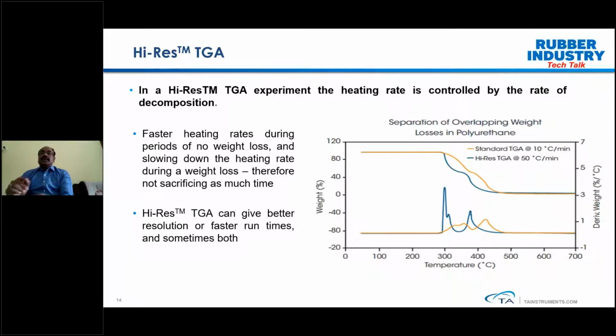Okay, so what we see is a much sharper peak, and you can see the clear shift of your decomposition pattern. But look at the derivative peaks. Now the derivative peaks clearly show sharp peaks. So now we are able to get the decomposition in a much better resolution, and we can also clearly separate those overlapping events. This is the clear advantage of high-res TG.